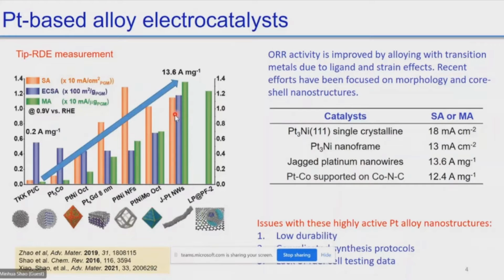All right. So now the problem here is that even the mass activity that you measured in the half cell, for example, the rotating disk electrode, most of the time cannot be realized in the real fuel cell, and that's the big issue. So I basically summarize the issues of recently developed highly active platinum alloy nanostructures. The first is there is no durability.